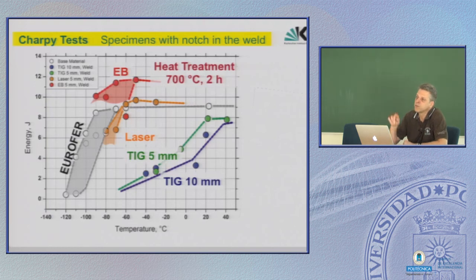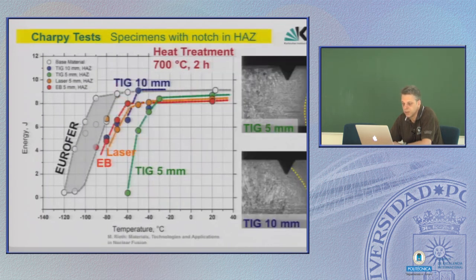The fractures in the Charpy tests propagate along the weld line, and in the base material they propagate straight through the material, and such bending in crack propagation requires higher energies, but this doesn't mean that this material is tougher than base material. DBTT, that's the right measure, and you see that's perfect here. So you could, in principle, live with electron beam welds, laser beam welds, with only a 700 C post-welding heat treatment, and then the beryllium pebbles won't suffer so much. So this could be a solution.